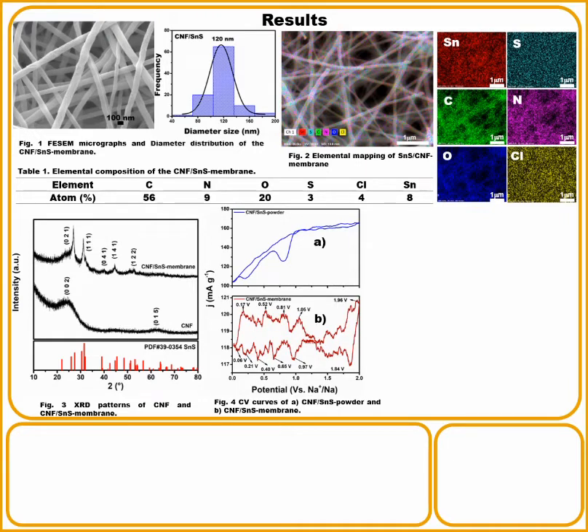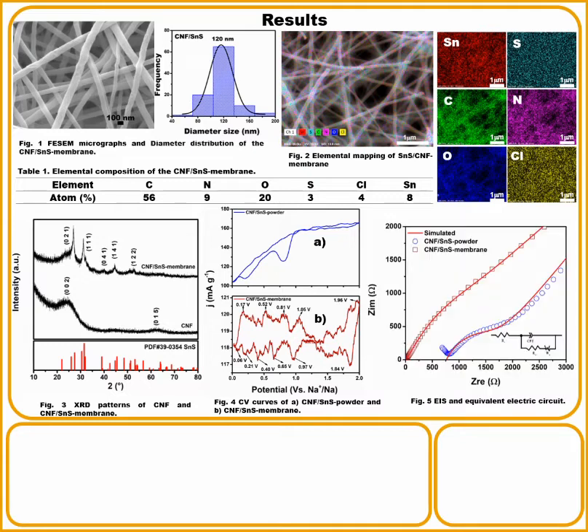Figure 4 shows the cyclic voltammetry curves of the carbon nanofiber powder with tin sulfide and the carbon nanofiber membrane with tin sulfide. The presence of the tin sulfide phase and other atoms in the membrane promotes multiple storage mechanisms of sodium ions, such as conversion reaction, alloying, and intercalation. However, the powder of carbon nanofiber with tin sulfide didn't present the reduction and oxidation peaks corresponding to the conversion, alloying, and intercalation of tin sulfide because it loses the ability to absorb sodium ions in this structure.